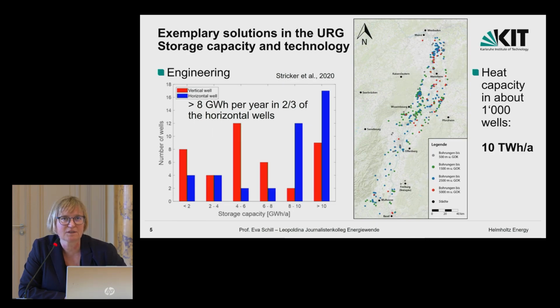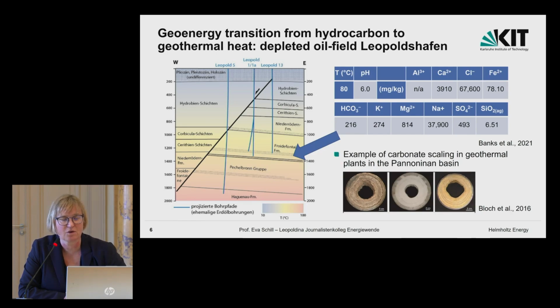When we analyzed this, we noticed that the way of engineering the reservoir has a big influence on the storage capacity, and you can see on the left side, when we engineer it with vertical wells, we have a rather distributed storage capacity, but if we use a horizontal well section, then you can see that the storage capacity moves to higher storage capacity. So we also now look into new technologies, because horizontal wells are not a challenge anymore in general, but they are a big challenge in this environment. Just to give you another number, for the storage capacity per Rhine Valley, if we only consider the oil fields, which we know, we would have a storage capacity of 10 terawatt hours per year, which is our number, and this is basically a minimum number. That's the challenge in this heat storage.